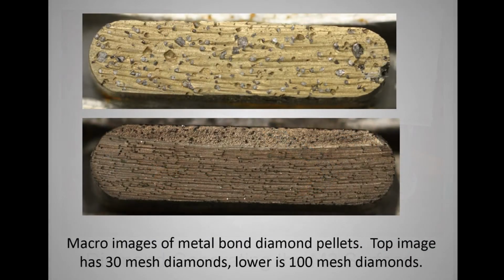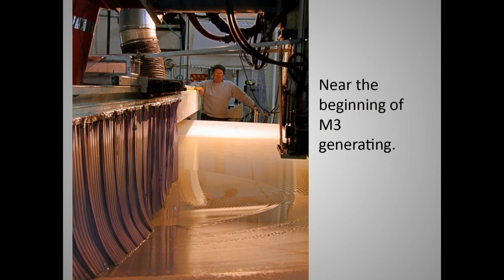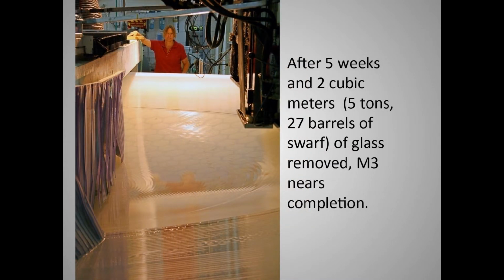When the diamonds get dull, they pull out and leave an empty socket where the diamond sat, and as the bond material wears away, it exposes fresh diamonds. We can take glass off at up to about a cubic centimeter per second, a few cubic inches per minute. Finer diamonds give you a smoother finish and less subsurface damage. Here's near the beginning of generating the M3 curve. This is towards the end. The black line on the outside was the goal. It's about 5 meters in diameter of the 8.4 meter surface.